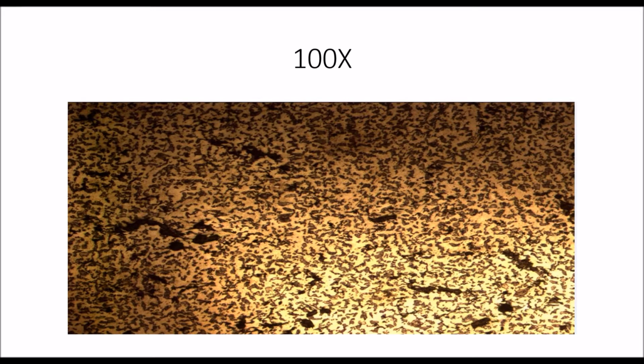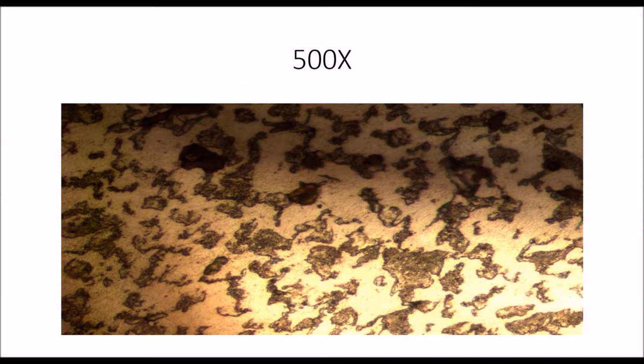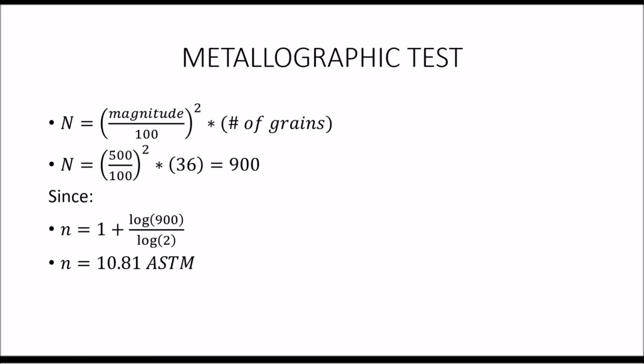In this test, we analyzed the count of grains at 100x, 500x, and 1000x. The photo that you are watching at this moment is the one at 100x, and this photo was taken just after I treated the bakelite in order to have a good quality. This photo that you are watching now is the metallographic test at 500x. As we can see, we have a clearer view of the grains, and with this photo I also made the analysis of the count of grains using the formula that we saw in class.